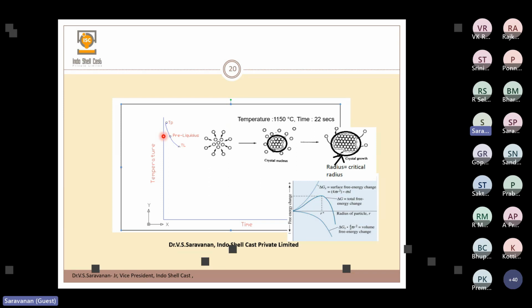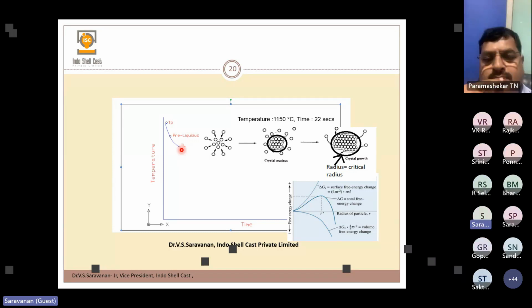This particular point is called the liquidus arrest, TL, sometimes TAL, whatever it may be. This is actually a permanent nucleation site, because the temperature drop at this particular point is sufficient to stabilize the nuclei. After the nuclei are formed, the kinetic energy is lost, so this temperature cannot split the nuclei into atoms again. They come close together and become stable. The heat in the metal at this point is not sufficient to dissolve these nuclei again. So this is actually the permanent one.